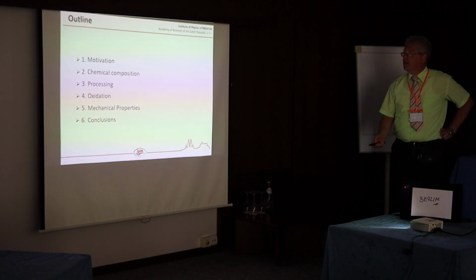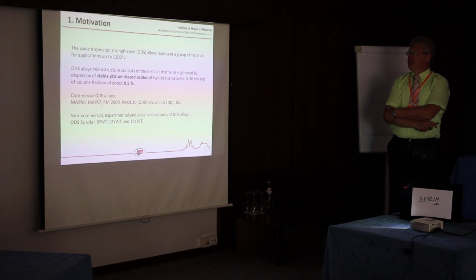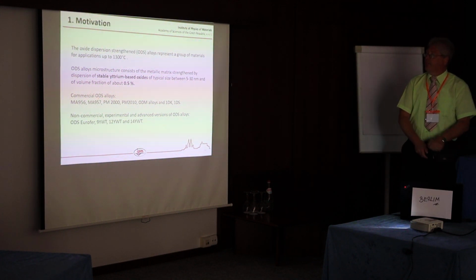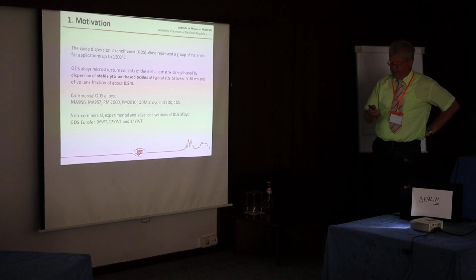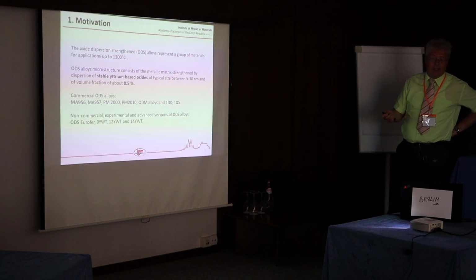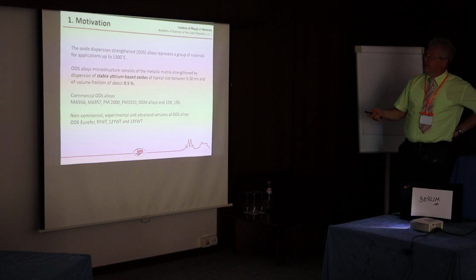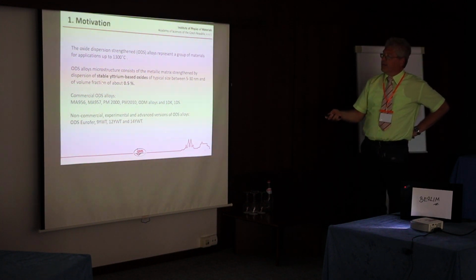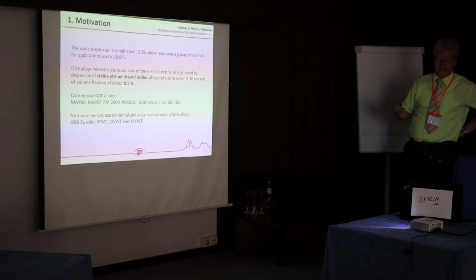So this is the outline of my talk. And the motivation is basically that we think that the potential of ODS alloys is still not fully used. They are investigated at lower temperatures, let's say up to 800 degrees. And since the yttrium particles are very stable particles and they don't coarsen at high temperatures over 1000 degrees, we aim to improve the current design of the ODS steels.